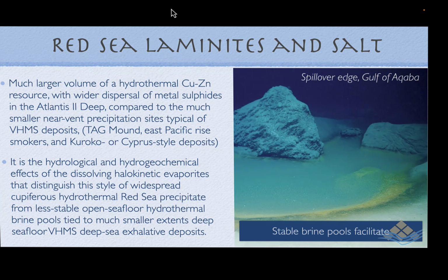The much larger volume of these hydrothermal copper-zinc resources within the deeps, compared to the much smaller volumes we see in near-vent precipitation sites of the typical VHMS, the volcanogenic hosted massive sulphide deposits such as TAG Mound on the East Pacific Rise, Smokers or Kuroko, or the Cyprus-style deposits, they're much smaller. And the big difference is the effect of that brine pool. And that is related to the hydrological and hydrogeochemical effects of dissolving nearby halokinetic Miocene salt.